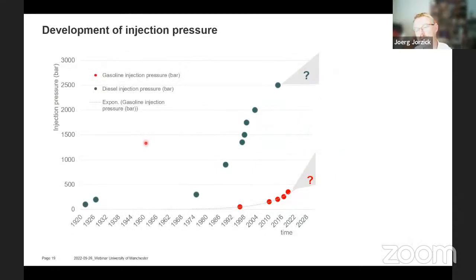So let's look a little bit, as I mentioned, about the history of the application from the automotive requirements from our customers. And I mentioned already that the coating was first applied with the injection systems, and it started with diesel. And here one of the major trends was the increasing injection pressure. And at a certain point, when the injection pressures were around 1,800 bar, the wear of the components became so huge, especially for the needle, that the sealing area needed to be coated. And as the pressures of the injection were further increasing, and right now we are typically at 2,500 bar, some systems are even higher, this is something that is still needed.